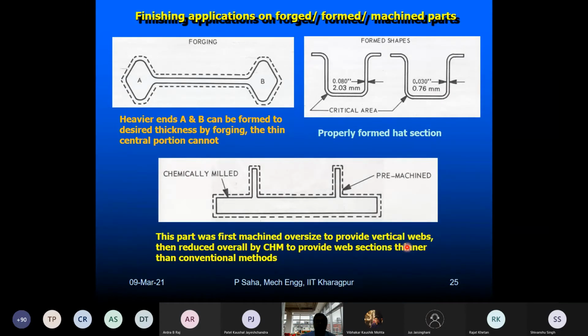So I will conclude this class with some applications. We have one or two minutes left. Before we conclude, suppose this is a dog bone or dumbbell kind of shape. Here I have to get this inner dark continuous line shape. The heavier ends can be formed by the forging process. But the problem is, when you attempt to obtain such thin dimensions in forging, the thin portions cannot survive. There may be cracks, and it may fail. So the best is to restrict forging to the much higher dimension, up to this dotted line, the central portions and all along, and the remaining portions you remove by the chemical route.